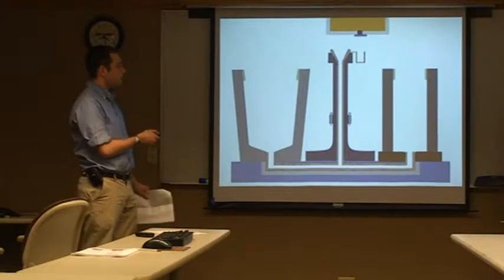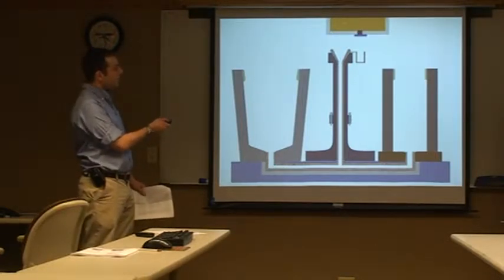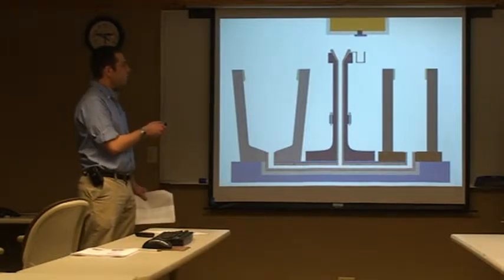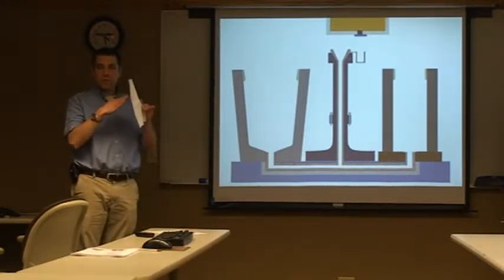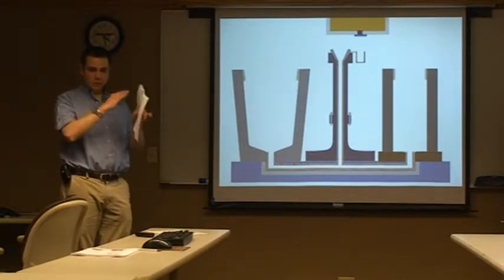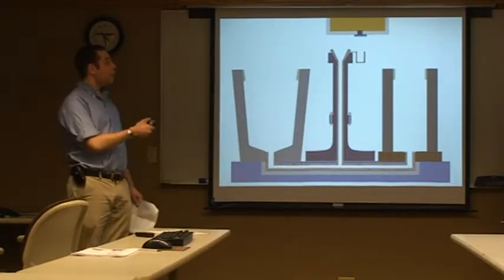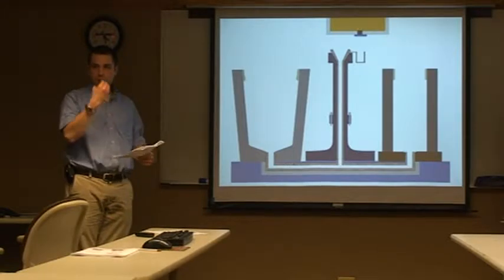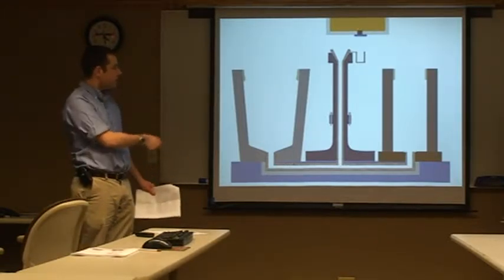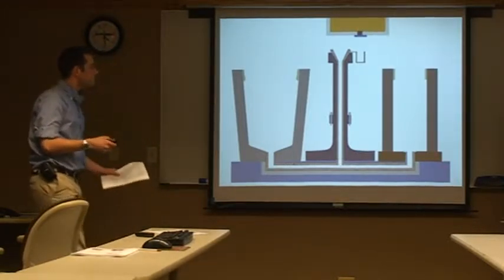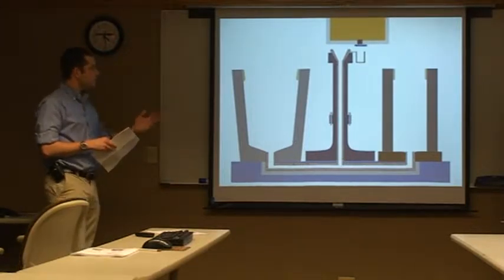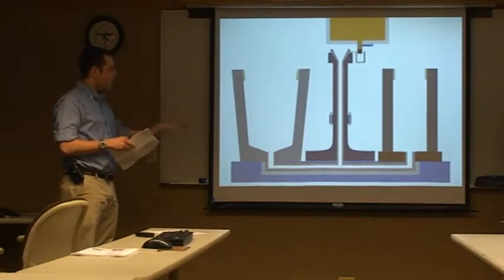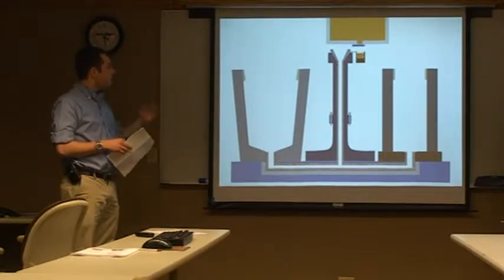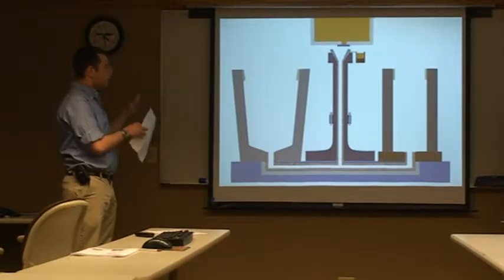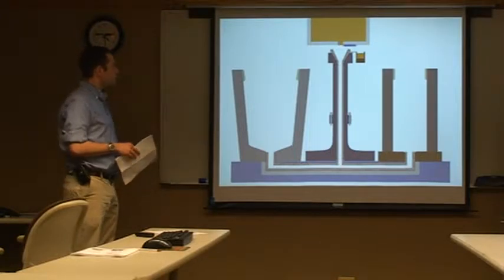So we'll use one of two processes. We'll either use a butt can, which is we empty the first bit of steel into here and then move over to the trumpet, or we'll use a cardboard tent over the top of the trumpet, which will deflect away any of the sand, and then when the liquid steel comes through, it'll burn through that cardboard and just start teaming into the molds. So here comes the ladle, slide gate opens, you get that first bit of steel in there, and then move the ladle over and start teaming into the molds.